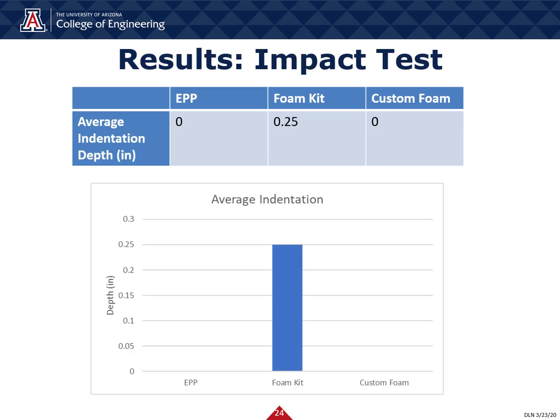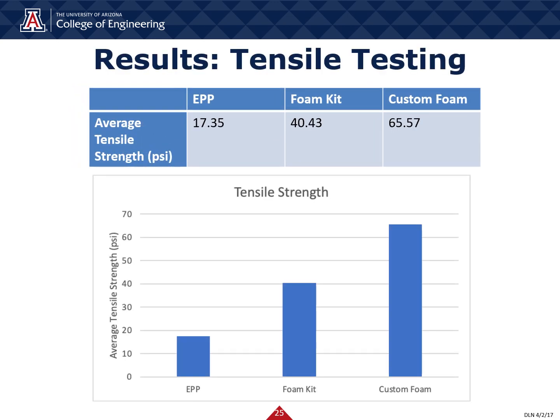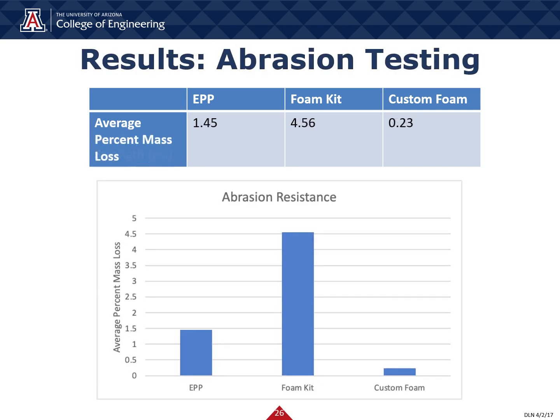Here are the results of the impact test. Only the foam kit produced an indentation, which was on average 1/4 of an inch. Here are the results of our tensile testing. The custom foam performed the best, requiring 65.57 psi for it to pull apart. The custom foam performed the best in abrasion testing as shown by the minimal lost mass, followed by EPP, while the foam kit performed the worst.